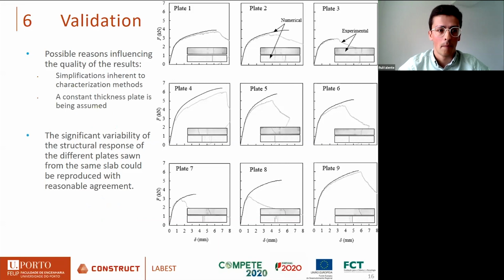Possible reasons influencing the quality of the results are the simplifications inherent to the characterization methods, namely the non-destructive test and the correlations with fiber content and fiber orientation factor. Also, human error in the NDT measurements. Also, simplifications of the surrogate models where we use simplified functions. And mainly, the main reason, in my opinion, is also the constant thickness of the plate, which is being assumed